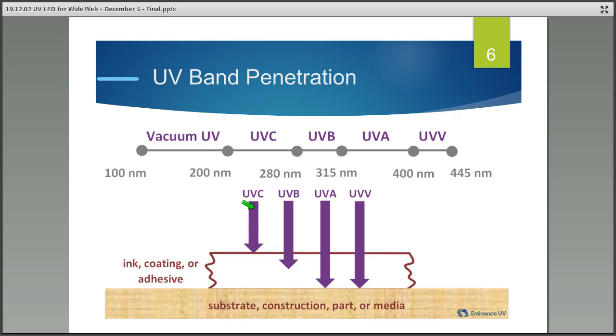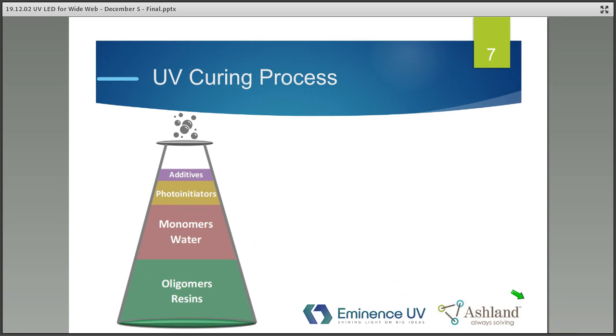The penetration of these bands varies. UVC tends to be absorbed at the surface. So this is what gives us good surface cure, which makes it not tacky, not greasy. UVB penetrates right below the surface. And then UVA and UVV have a much longer wavelength and therefore penetrate all the way down to the construction, which makes sure that you're getting cure and good adhesion to whatever you're printing on.